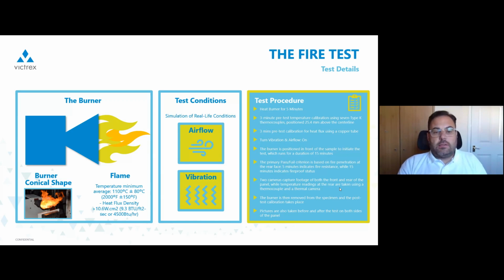So you would turn the burner on and leave it to stabilize for 3 minutes. Then, as you can see on the lower left-hand of the picture, you would have type K thermocouples to make sure that your fire temperature is within the required range. So you do a calibration for 5 minutes. You do a similar thing for the heat flux. The heat flux is done by measuring with a copper tube with water in, and you measure the temperature difference, to make sure that you have the right amount of heat flux coming through. Then the burner is moved into position. Again, the position of the burner is preset, everything is in the standards, and you would start the test.